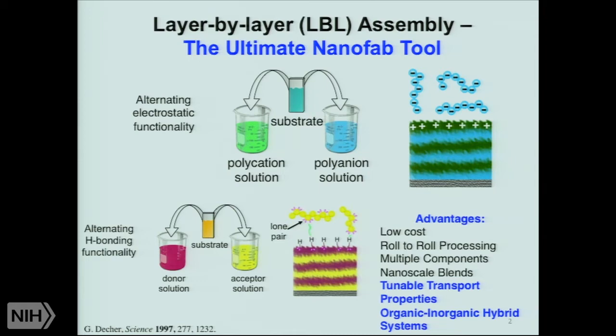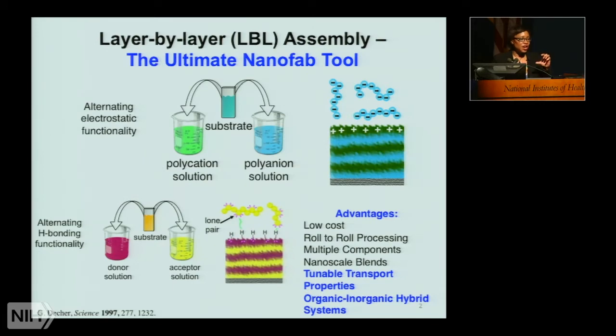And we can continue this alternating plus and minus to generate these multi-layered thin films. Now, I show these as green and blue stripes, but in reality, when they're polymeric material systems, they're highly interpenetrated. However, you can get definition within plus or minus 4 layers, which means that if you create a series of layers which have one composition and cap them with a series of layers of another composition, you can create either gradients or systems which have 2 or more delivery systems combined.